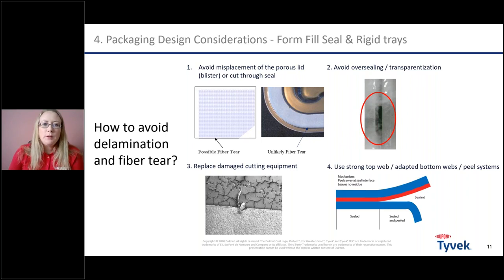For example, on the first one, you see a blister or a tray from top view. You can see the tray shining through in blue, and then the white is the Tyvek lid. So when both go to the edge, so the lid and the tray flange, then there is some risk of fiber tear, because you can seal in some filaments here and that can propagate. Or you cut through the seal, that's the same issue. So the recommendation here is clearly to have some unsealed gap between the seal and the edge, or you can even design, like here on the picture, a flange into the tray if you have a rigid tray. So different ways of realizing that.